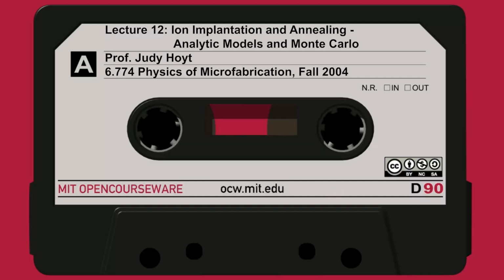So people do, as we see here on slide 28, something called controlled misalignment of the crystal when they put the wafers in the ion implanter. And they don't put them in like this. They try not to put them in so you're looking straight down the 100 axis. What they do is they take the wafer and they put it on the plate and they tilt the plate a little bit with respect to the beam. In fact, typical tilts are about 7 degrees. And they actually also rotate it.